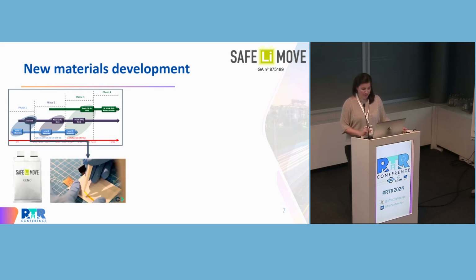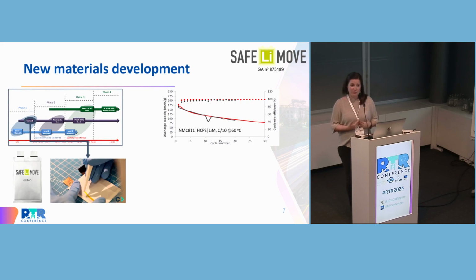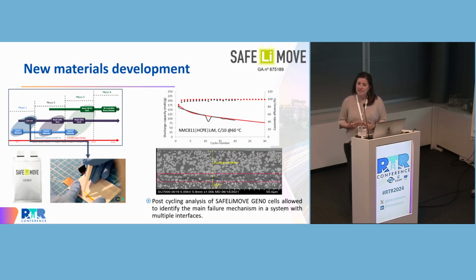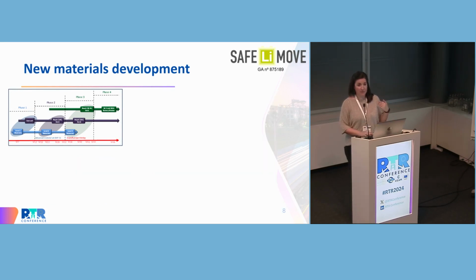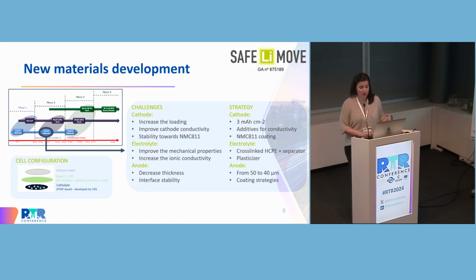All these materials were transferred to the partner in charge of manufacturing the cells, TDTech in this case, and they produced the first coin cells and the first monolayer pouch cells. So the main outcome of this, so for sure this was in month 7 of the project, we were not looking for results, the KPIs, but the most important outcome that we got here is the compatibility of all these materials when we were putting them together. We need to consider that each material was provided by a different partner, so it was really important to make this checkup. And then also we analyzed the cross-section and the post-mortem of this cell. So what is the failure mechanism? What is the degradation or the failing issue of my battery? And thanks to this, we understood where our challenges were and how we could solve them.